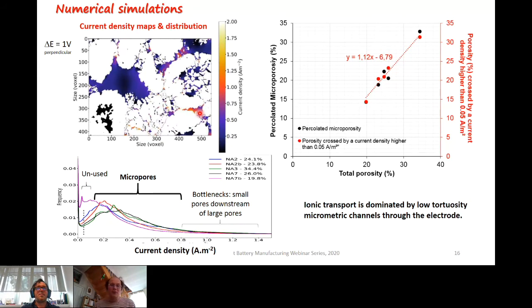There are some micropores in which the current density is high. It's because these micropores are small and they are downstream of larger pores, so they are forming bottlenecks. And you can also observe that in the nanopores, you may have a high current density, but these nanopores represent a very tiny volume of the total porosity, so they likely don't play a major role. What you can also observe is that inside the hollow fractured clusters, there's a fraction of micropores that are crossed by a low current, in black here.